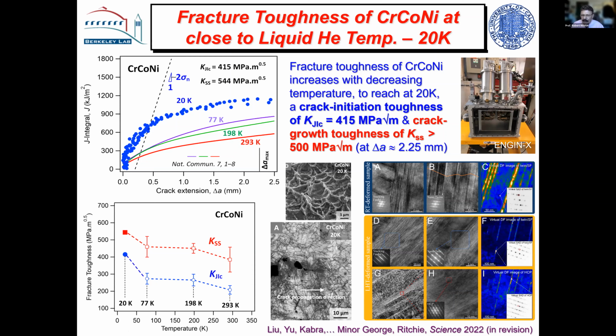So there's something magical about these materials. And they are, remember, the simplest structure imaginable. They're just equiaxed grains, single phase. But we can get remarkable toughness. It's all ductile fracture. And if you look at the mechanisms when you get down to liquid helium, then everything is that much finer and that much more planar. You can see this is an EBSD, masses of twins everywhere. You don't even see dislocations because the stacking energy obviously gets lower and the stacking faults extend dramatically. But this sequence of dislocation slip, stacking fault formation, twinning, and TRIP to form the hexagonal phase, but there's very little of that hexagonal phase. You don't get a lot of it. Seems to generate this remarkable strain hardening, which gives us these ridiculously high toughnesses.